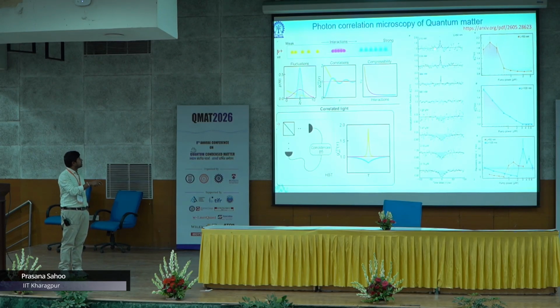So indeed, if you look at that confinement potential, when you have very low light, 200 nanowatt, one could expect a single photon, but rather we get G2 more than 1. But when you increase the power, one could expect this value to increase, but it is switching over from a classical to a non-classical light.